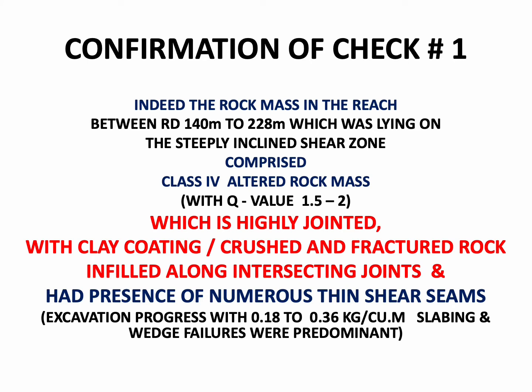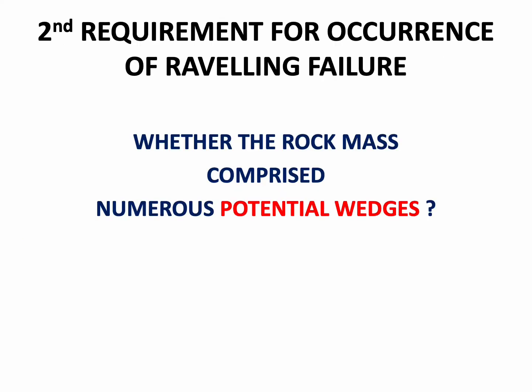So it is confirmed that the first prerequisite is met. Indeed, the rock mass in reach between RD 140 to 228 meter, which was lying on the steeply inclined shear zone, comprised class 4 altered rock mass with Q value of 1.5 to 2, which is highly jointed with clay coating and crushed and fractured rock infilled along intersecting joints, and had presence of numerous thin shear seams. So this confirms that the first prerequisite, which makes the rock mass highly jointed, was present there.